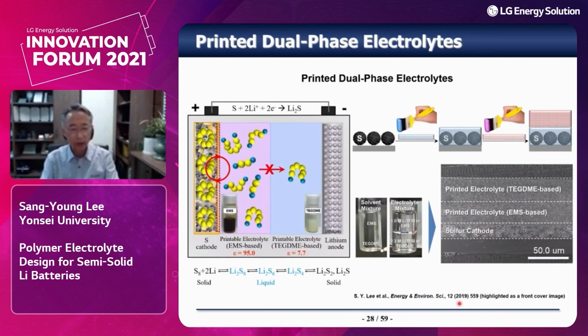So here is our result. We have suggested the printed dual phase electrolyte as a representative example. We have chosen a lithium sulfur cell. At the sulfur cathode, the sulfur cathode prefers a polar solvent to facilitate the dissolution of sulfur. However, this polar solvent is not good for the lithium anode side. So we have separated them by using the dual phase electrolyte concept. We have chosen EMS as a solvent for the cathode and TEGDME for the anode side.